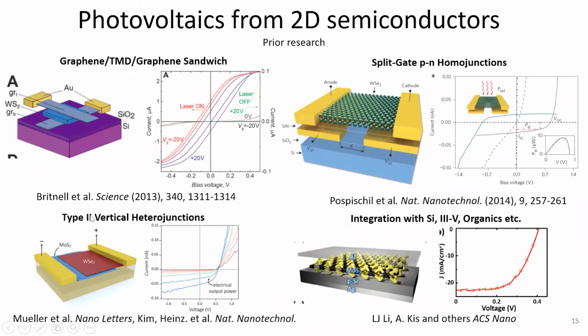Likewise, people have found that you can have type 2 junctions formed between MoS2 and WSe2, two of the most popular combinations, and when you stack them vertically, you can get a photovoltaic effect. Likewise, people have tried to grow them laterally or stitch them in plane, and people have also observed photovoltaic effect in that. So there has also been a lot of work in that area. And finally, a lot of work has also focused on integrating MoS2 or other chalcogenides directly with silicon or gallium arsenide or indium phosphide.